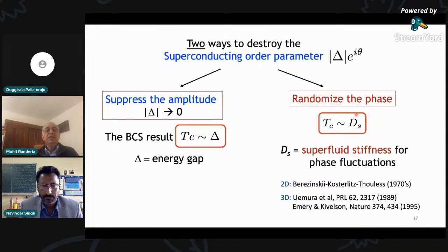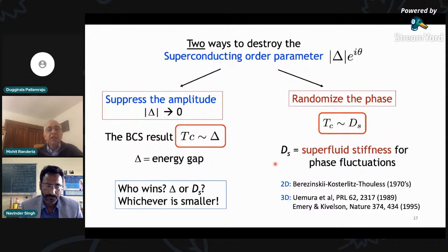From these pictures, it seems that the transition temperature should be determined not by the energy gap, but rather by the stiffness for phase fluctuations. Because after all, what randomizes the phase is, if the stiffness is small, it's very easy to randomize the phase. If the stiffness is large, then the phase does not want to get randomized. So that then raises the question, who wins, the BCS gap or the superfluid stiffness? And the answer, as we will see several slides down the road, is whichever is smaller, which makes perfect physical sense, because if you have an ordered state, whatever can destroy the order will destroy the order. You raise the temperature, if you first hit the gap scale, that kills you. Or if you first hit the superfluid stiffness scale, that kills you.